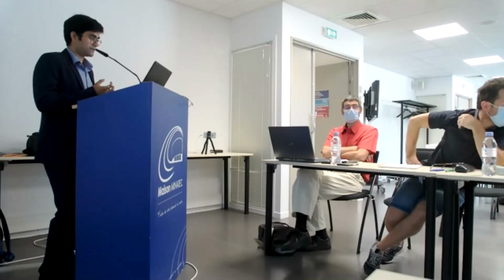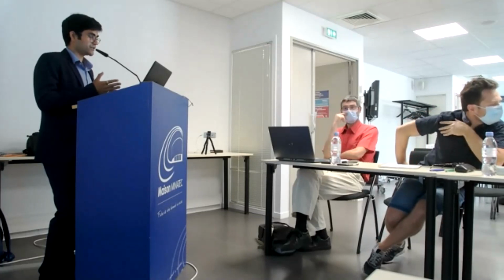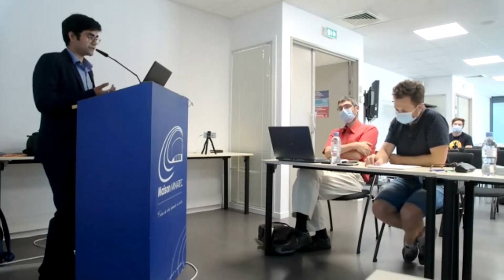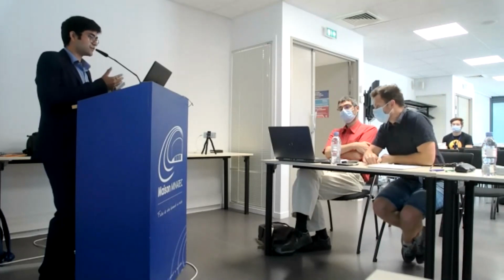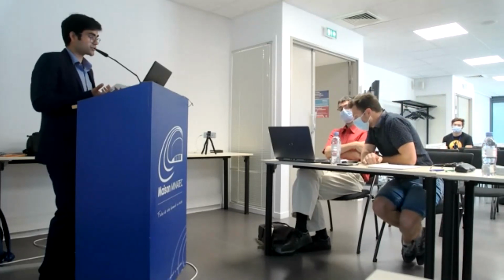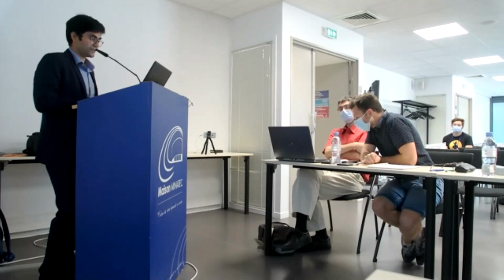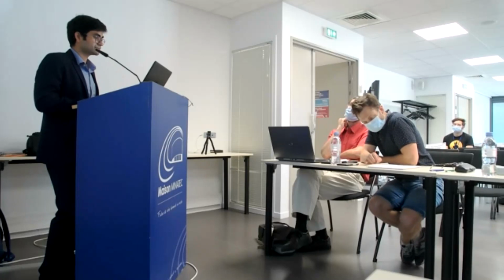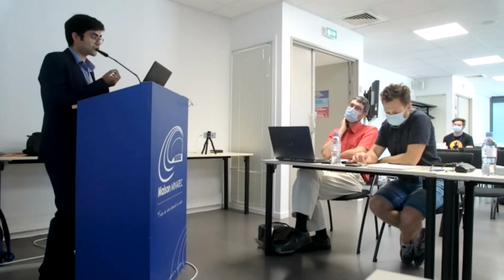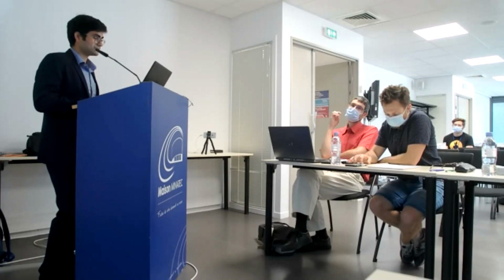Yeah, I agree. Based on our thermodynamic simulations with the Scheil-Gulliver model as well, we found that certain elements have a low partition coefficient, depending on the different elements we selected. So certain elements might have different partition coefficients, and this might lead to selective segregation along the grain boundaries. But to confirm this, we might need ASTAR or even tomography. Do you think atom probe tomography could really quantitatively measure the segregation aspect? Yeah, okay. Atom probe tomography, I agree, but not tomography. Yeah, atom probe tomography, I meant. Well, maybe holotomography could reveal that, the advantage would be the statistics. But yeah, for sure.